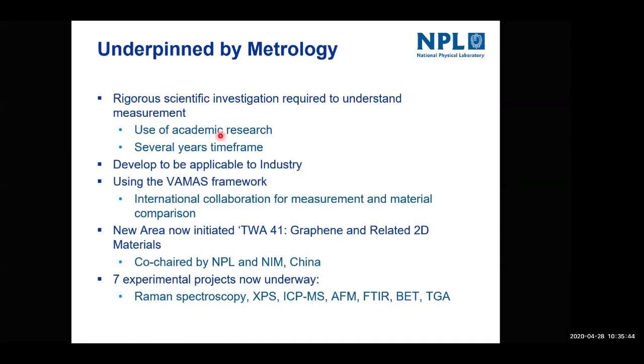So a really important thing to say on top of all of this is that when we're standardizing these materials, it's really important that it's underpinned by metrology. What does that mean? Well, it doesn't mean that we've just done a measurement somewhere and said, okay, let's standardize this. What it means is that we've validated these measurements. And we do that through international round robin and inter-laboratory studies, where essentially we take the same material, the same protocol, and measure it at labs across the world, and then look at what the variation is of the values that we get. Now, this is because it's always different between labs, and that can be for many different reasons, but essentially it gives you an idea then as an end user.